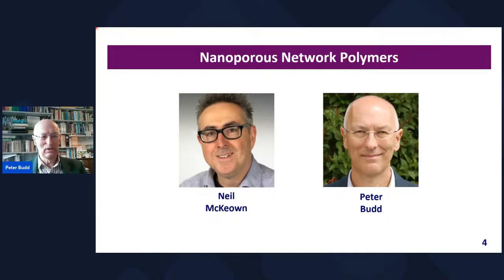Now, Neil was an expert in phthalocyanines, and phthalocyanines are big plate-like molecules which have a metal ion at the center, which can take part in various sorts of catalytic reactions. But phthalocyanines, these sort of flat plate-like molecules, tend to stack together. And so what we were trying to do at that time was to build phthalocyanines and similar molecules into a polymer network in such a way that the plate-like molecules were prevented from stacking.